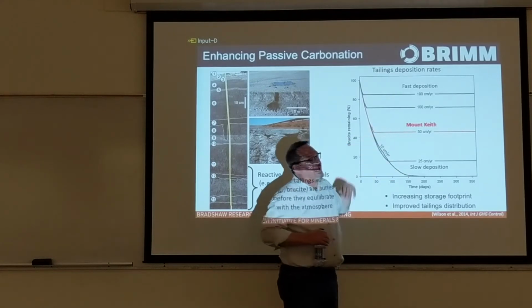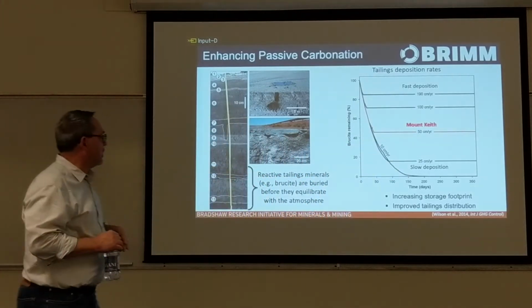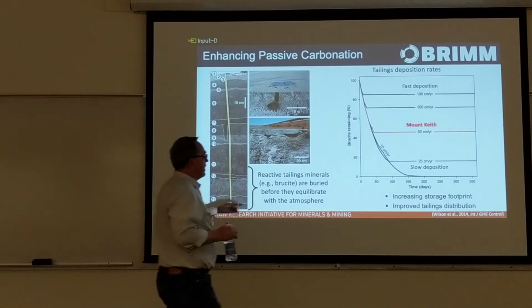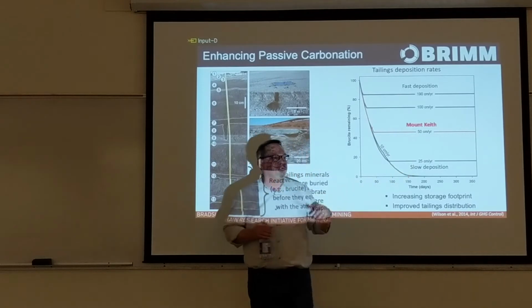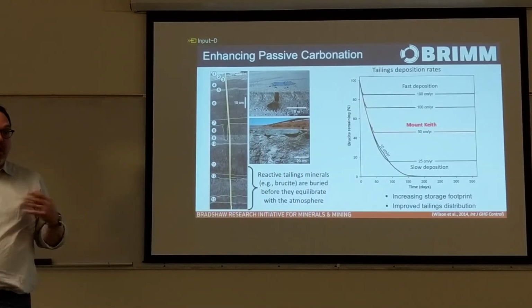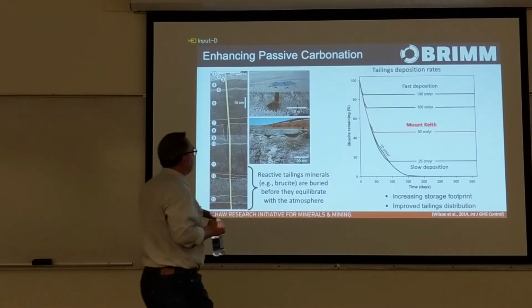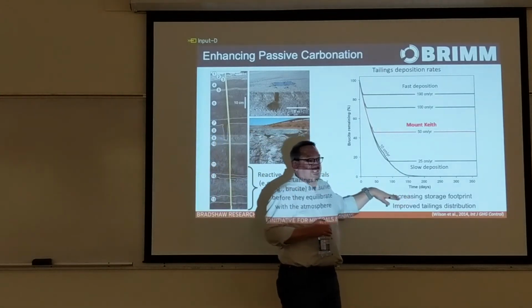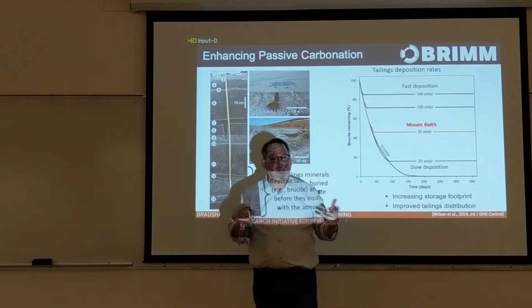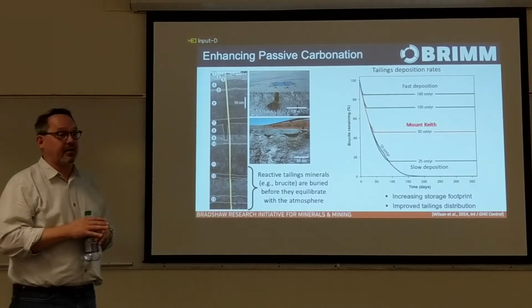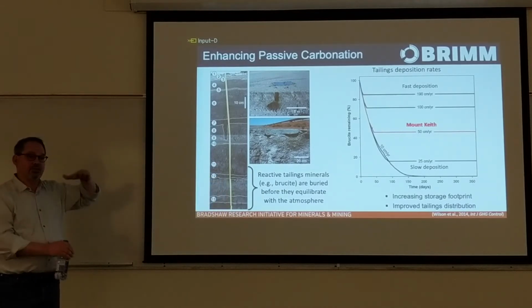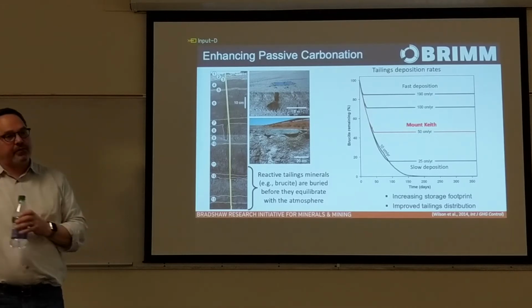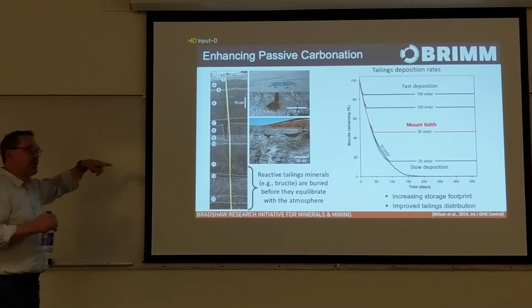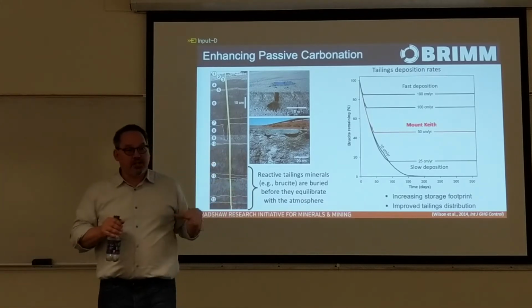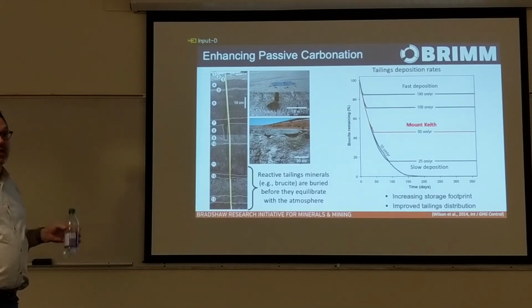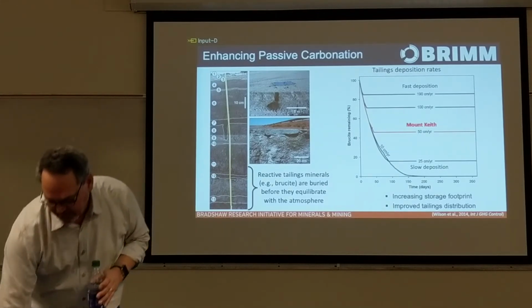They're burying about half their labile magnesium. If they put down tailings flows that were about 10 centimeters thick rather than 50 centimeters thick, they could essentially react all that labile magnesium before they bury it. So they would double their CO2 sequestration rate simply by putting down thinner flows of tailings. You could do that by increasing the tailings storage footprint, but you could also do it by simply turning on the tailings distribution spigots more frequently. Right now they have 5 risers, and they will run 2 until the flows get a certain taper in the tailings pile, and then they'll turn those off and turn other ones on. They could create thinner flows by simply turning those caps on and off more quickly and increase their uptake rate without redesigning their tailings storage facility, really just changing their operations.